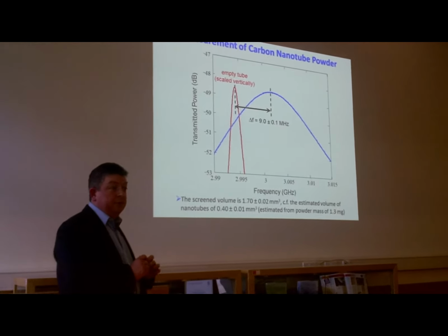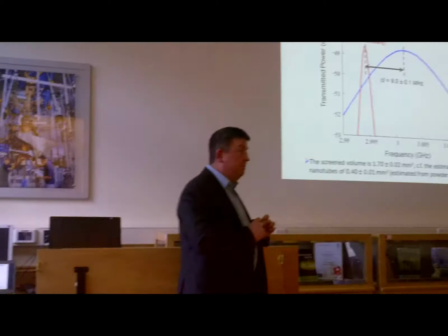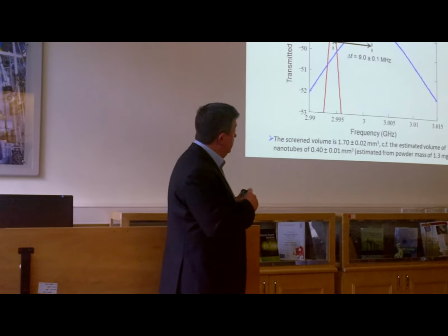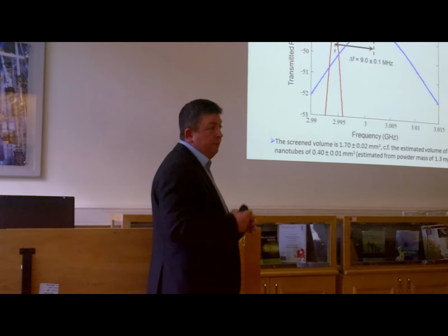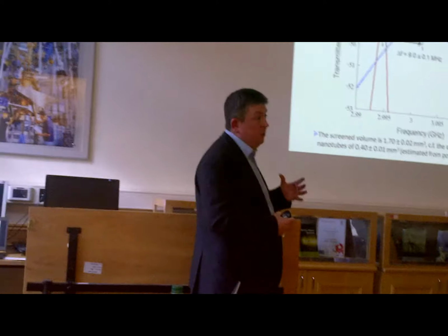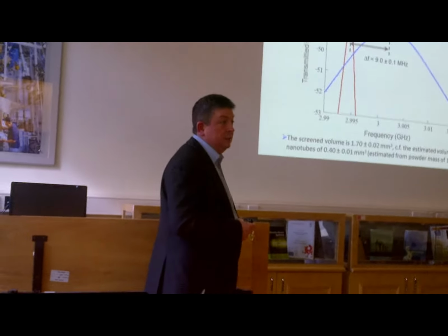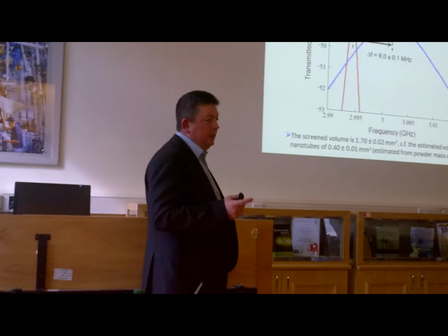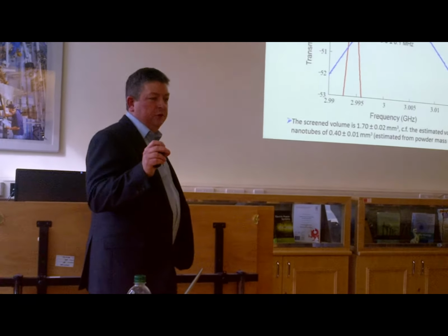If you do the same measurements on conducting carbon nanotubes, then you get a very remarkable result, really. At least that's what I first thought about it: you end up with a frequency increase as a result of the material going into this magnetic field region. And that is a classic example of conductivity being large enough that you see the effect of skin depth.